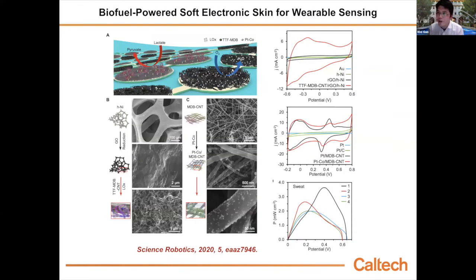Nanotechnology plays a very important role here. As you can see, we immobilized our biofuel cell anode with nickel nanostructure, followed by graphene coating and carbon nanotube coating. For the cathode, we use the carbon nanotube network followed by platinum cobalt nanoparticle decoration. Using this nanomaterial, we can enhance the active electrocatalytic surface area by 3,000 times.